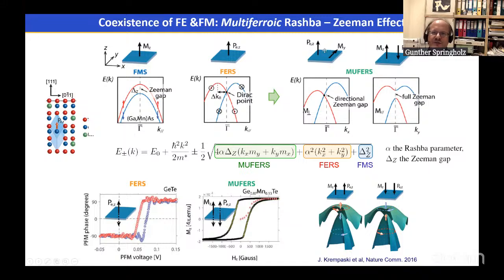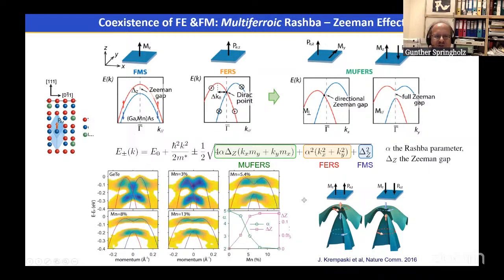Of course, the situation is more complex because the magnetization and polarization can in principle be not collinear, but in different directions. And so there's a complicated spin texture evolving as a function of how the electric polarization and the magnetization are oriented relative to each other. So here's an example of the measurements of germanium telluride with these Rashba bands here. And if we add manganese, then there's this Zeeman gap opening here, as is shown in this cartoon on the upper right-hand side.